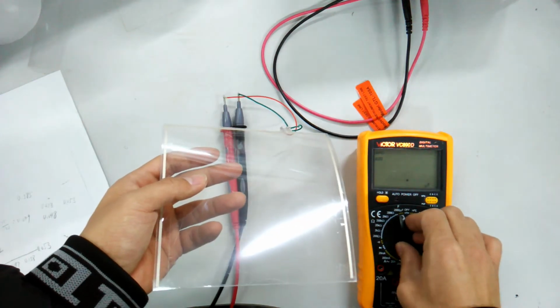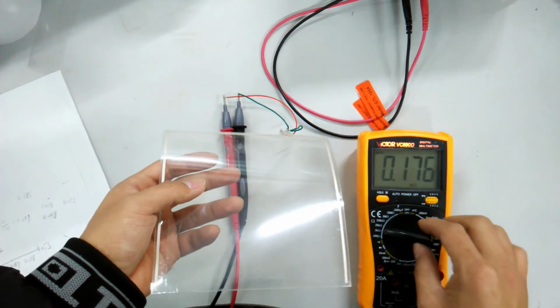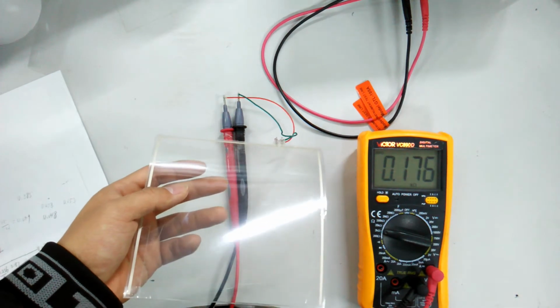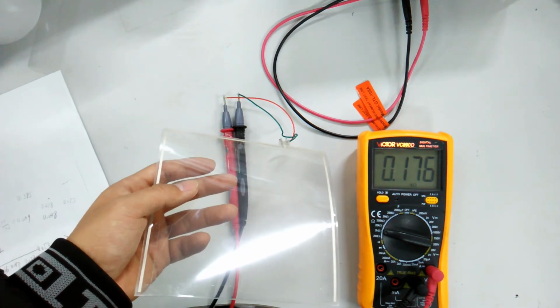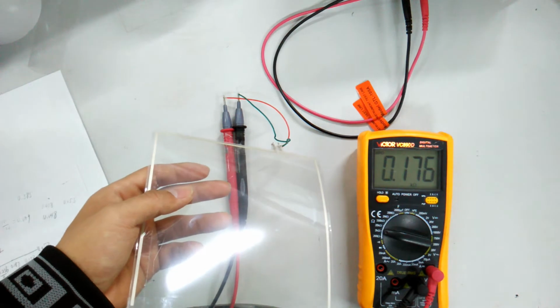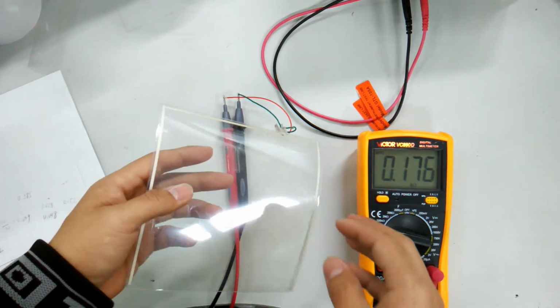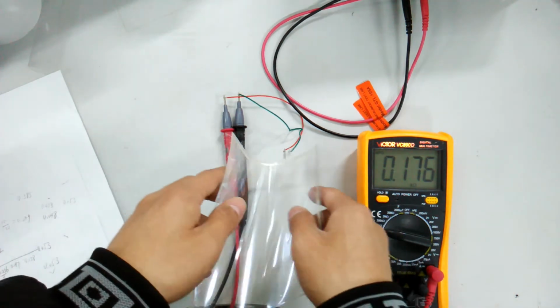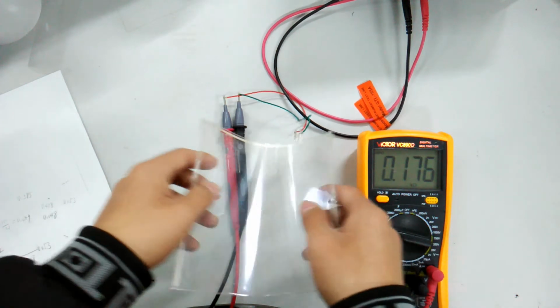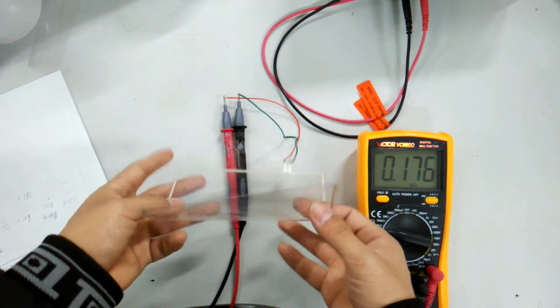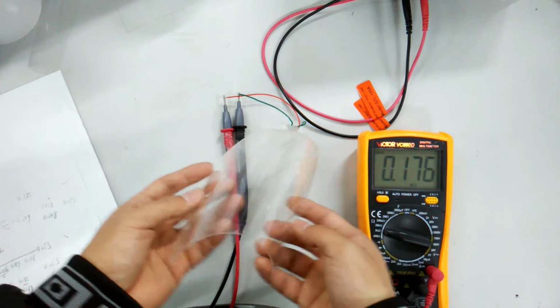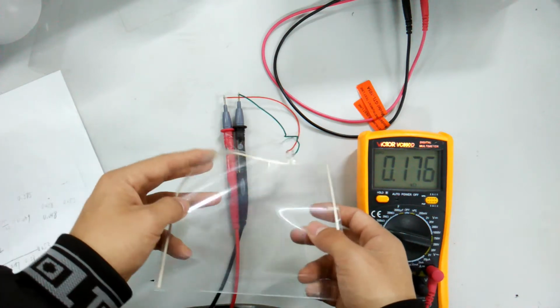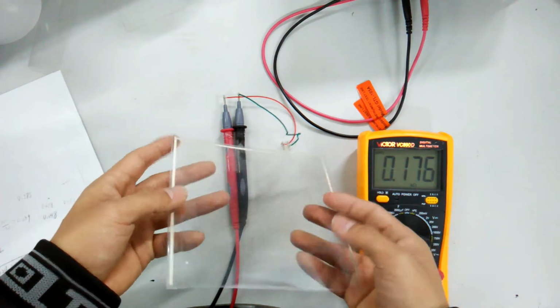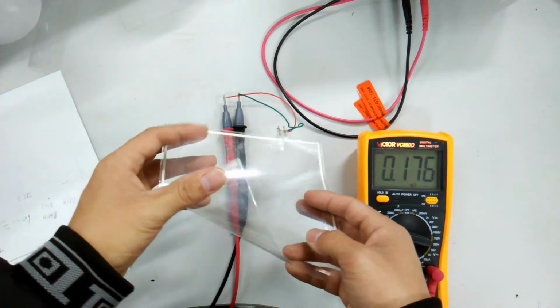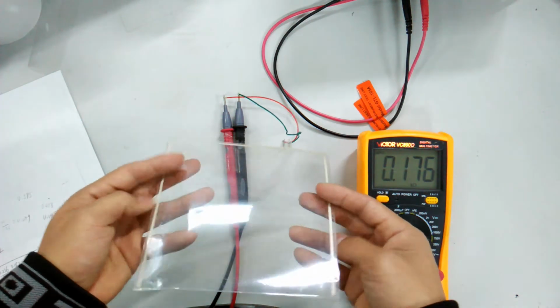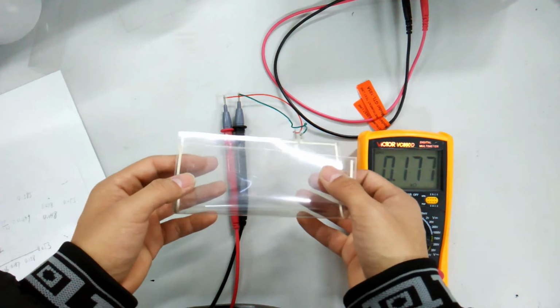We switch the multimeter to the ohm. We can see the sheet resistance of this ITO film is 176 ohm per square. The inconsistency with parameters given at the beginning of video may be due to the non-standard fabrication of the electrodes. But this does not affect the sensor operation because the sensor operates on the detection voltage. We can see that the resistance measured by the multimeter is almost constant under normal bending conditions.